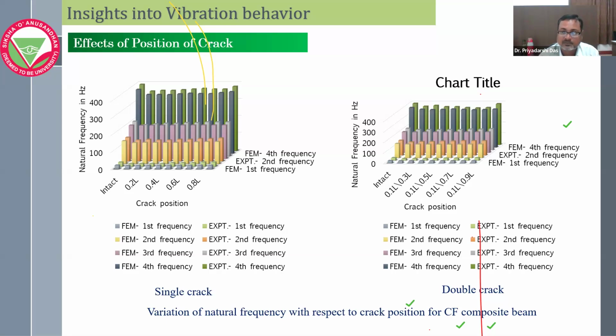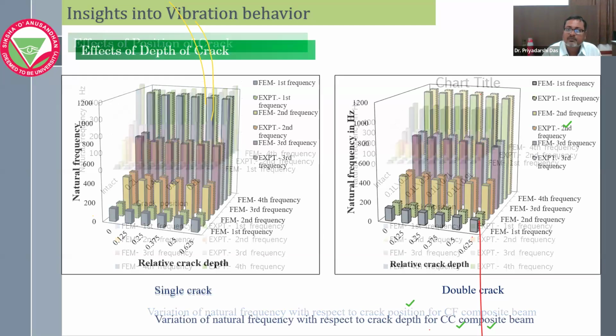Now if you go for the third crack position, the crack needs to be fixed at 0.1 L and 0.3 L, and the third crack must be varied from 0.4 L to 0.9 L. So this is a sequential approach to quantify, a sequential approach to describe the crack behavior inside the laminated structure. In this way, we can easily identify where the disintegration happens and how the structural behavior is affected through the initiation of the crack. The same thing we have adopted for the effect of the crack depth.